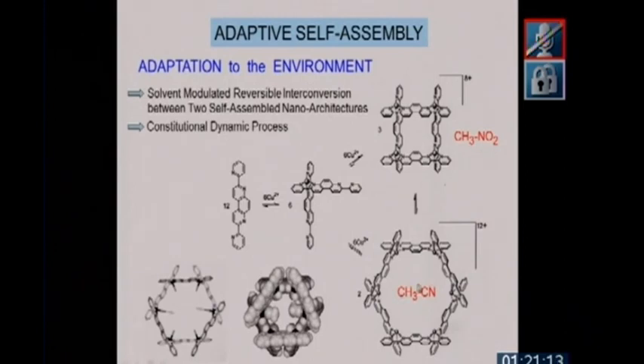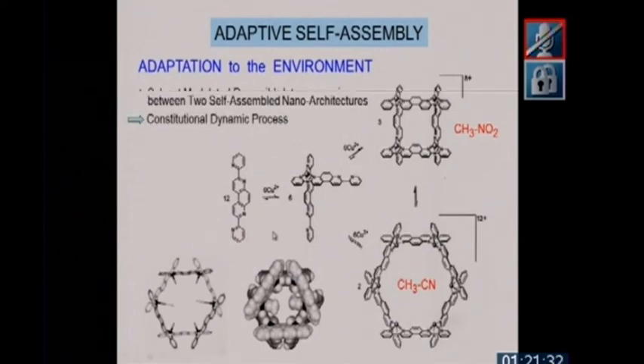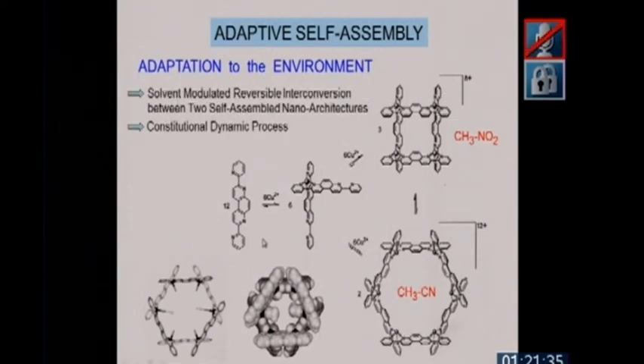If you go to acetonitrile, acetonitrile has a nitrogen which is a much better coordinating center. So this forces the system to generate a unit where the acetonitrile can coordinate. That means it opens up, generates a hexagon, and is this rather large hexagon, as shown by the crystal structure shown here, acetonitrile molecules connect to the coppers. You see here, acetonitrile molecules connected to copper inside the cavity, as shown here. So that is a case where the different solvents induce a different assembly. And indeed, when you add acetonitrile to this solution, you go progressively over from the grid 2 by 2 to the hexagon.